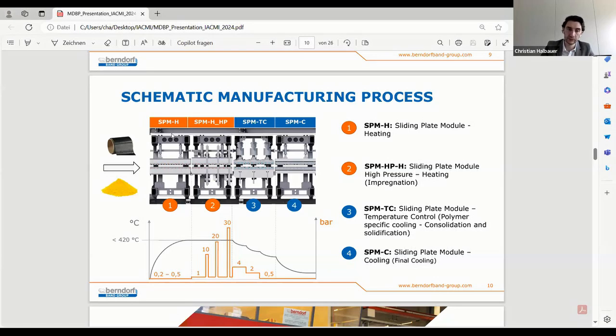At the entrance, once we reach the first module, it's called the sliding plate module for heating. It's like preheating at a very low temperature level. As you can see here, we would go with up to 0.2 to 0.5 bar and increase the temperature up to 420 degrees, depending on the type of polymer you're using, could be PA6, PA12, PEEK, PPS, PPA. So we're used to various kinds of them. We even have the possibility to divide the plates into 2 sections, again to make the preheating a gradual process.